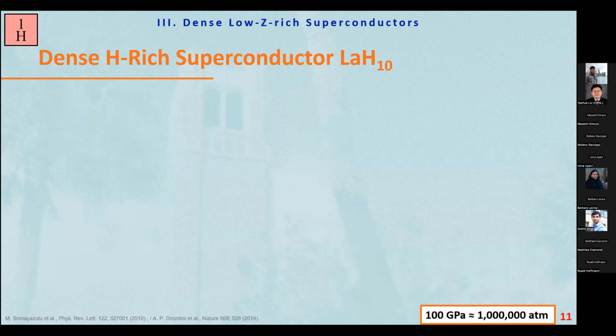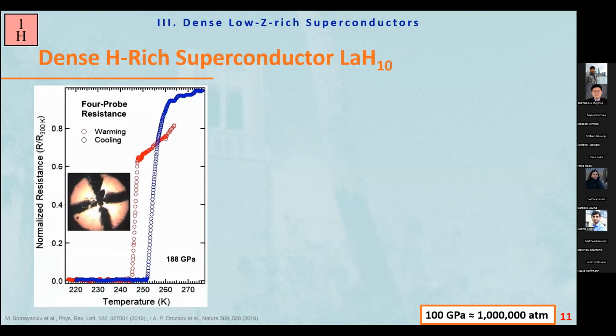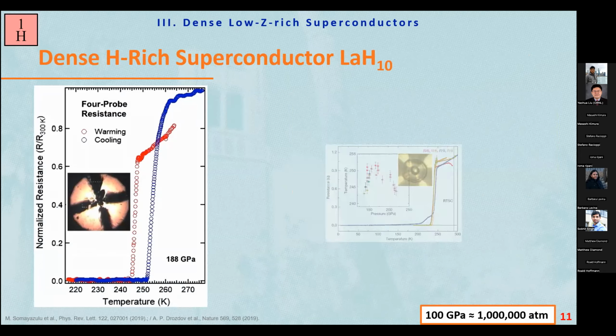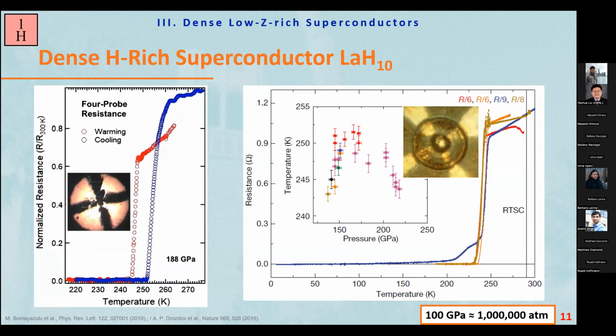That first superconducting hydride was H3S, and then a follow-up study showed that lanthanum hydrogen 10 has a very high TC at high pressure. So two groups produced this high temperature superconductivity in lanthanum hydrogen 10. And an interesting point is that hydrogen forms a cage-like structure surrounding the lanthanum inside. And that's the distinct picture of this system.